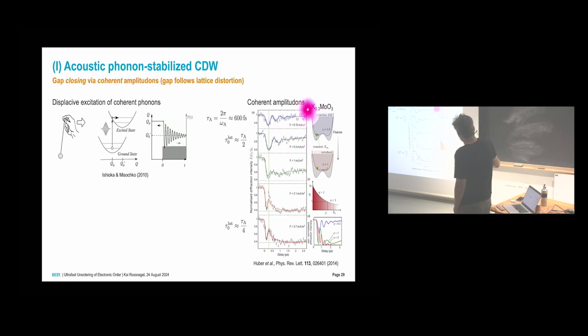And then you excite your potential energy surface and you start to oscillate here at low fluence. At harder pumping, you drive the system into this type of form, not the double well potential, single well, and then you have this overshoot scenario. And this means here you want to go to this point here, 0. This is 0 amplitude. This is removal of the distortion. If you have this overshoot scenario, then you end up with a quarter period. It's a quarter period, it's the fastest time scale.